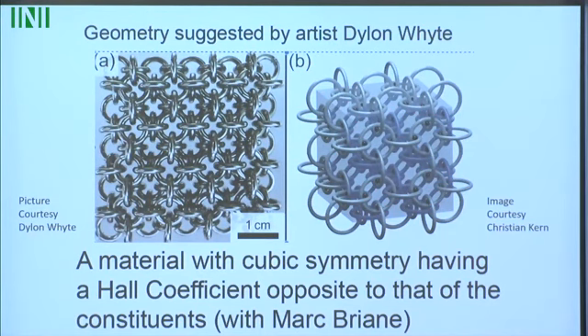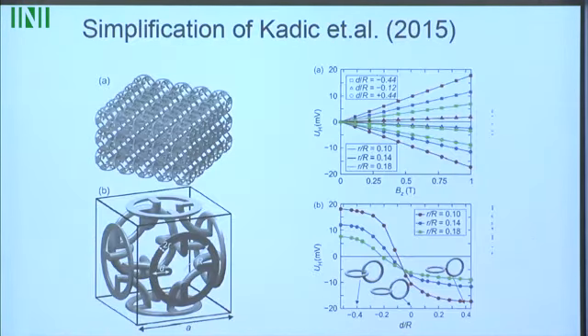It was a 3-dimensional geometry of interlocking rings. Here, this is a photo of 2 layers, an actual photograph of rings built up by Dylan White. And in 3 dimensions, the geometry looks like this. The cofactor matrix changes sign in the gaps here, and this is where you put your material with a high positive Hall coefficient. That was a bit difficult to build, so the group of Martin Wegener found a simplified geometry. You've still got the interlocking rings, but they're linked by a conducting bridge. Now everything is built from one phase, and that phase could be a semiconductor.